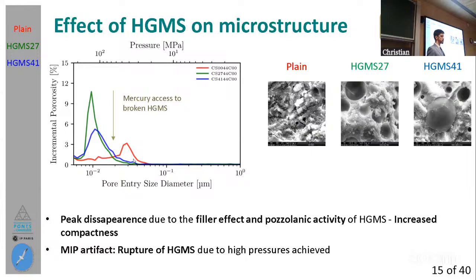And first, I want to focus on this little peak here with the plain cement paste. You will see that for these pore entry size diameters, for the paste with the spheres, this peak disappears. This could be related to the filler effect and pozzolanic activity enhancing the compactness of the material, which can also be seen somehow in these SEM images here. You can see a less compact material in the plain cement paste than in the cement paste with HGMS27 and HGMS41.